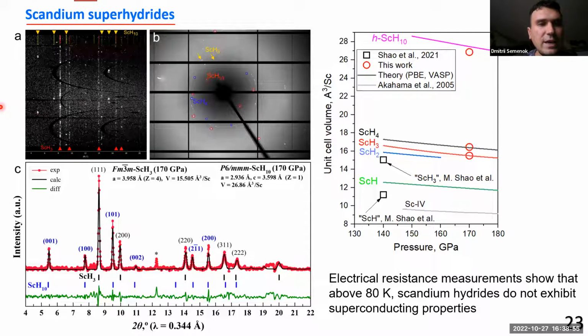In the second pattern, we detected a new compound with much higher hydrogen content than in scandium H4. You can look at picture C. We have several diffraction peaks at low diffraction angle, low 2 theta. It's about 5.5, and the next is 7.5, which shows us that the hydrogen content in this new compound is much higher than the hydrogen content in scandium H3, which is still the main product of the reaction. And we can explain almost all diffraction peaks observed in the experiment using the hexagonal P6/mmm scandium H10 structure with those unit cell parameters. You can see it here,